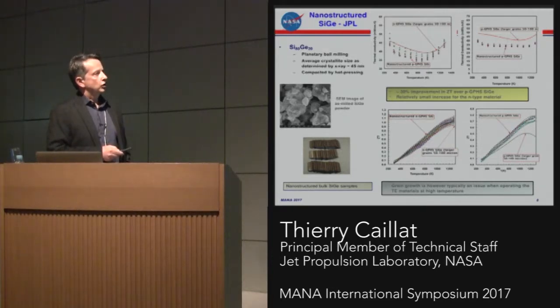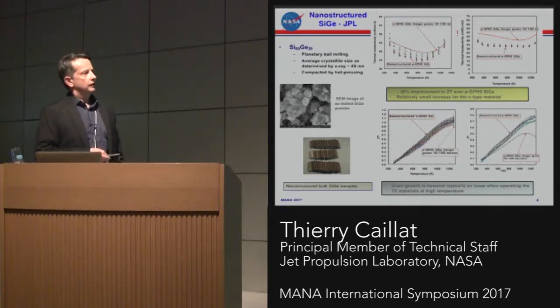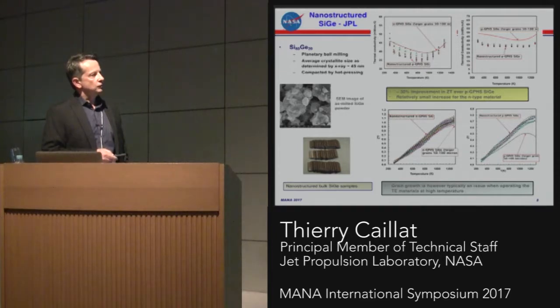These two plots are showing the P-type and N-type. There's a typo here. I think one should be the N-type. This is N-type. This is a baseline, what's being used in Voyager, for example, with fairly large micron size grains. And you can see the reduction that you can get by doing the nanostructuring through ball milling. It's a matter of how much carrier mobility loss you incur during the process. It turns out if you can increase the carrier mobility over the lattice thermal conductivity, then you get an increase in the ZT itself. Typically the ZT in the N-type, even the baseline, is higher than the P-type, so we don't see much of a gain by doing nanostructuring on the N-type, but you do see some substantial gain on the P-type.